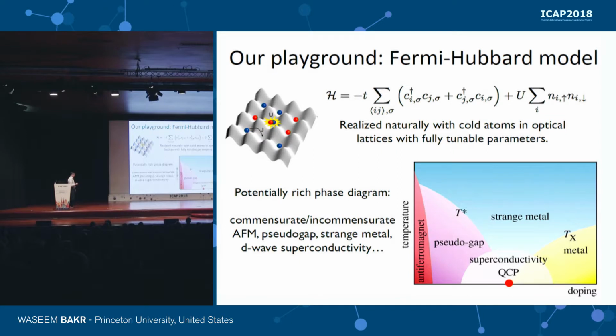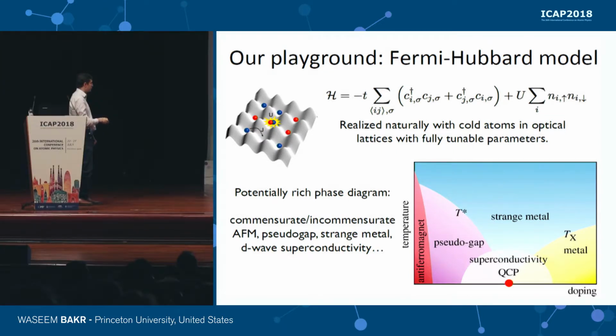So at high temperatures, but below the interaction energy scale, you get a Mott insulator, and then as you lower the temperature, you get antiferromagnetic correlations. These experiments have been seen in cold atoms, of course. But where fewer experiments have happened, and what's less theoretically understood, is the doped regime.